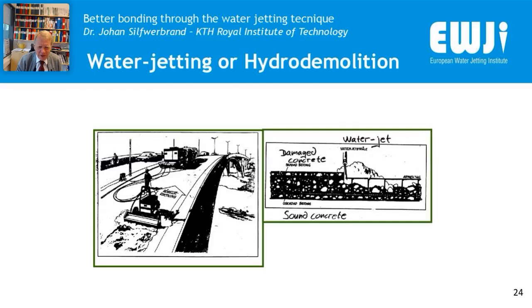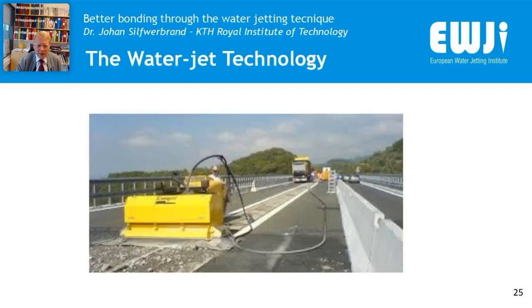And so the water jet technology works with a thin water jet. It builds up a water pressure inside your concrete, and when the water pressure exceeds the tensile strength of concrete, the concrete spalls. And if your concrete contains a lot of cracks, a lot of pores, other types of distresses, and if it is of poor quality, the water jet technology works much more efficiently, and that's why it is also selective, that it removes poor concrete and it leaves good concrete. And you know much more about water jet technology than I do.